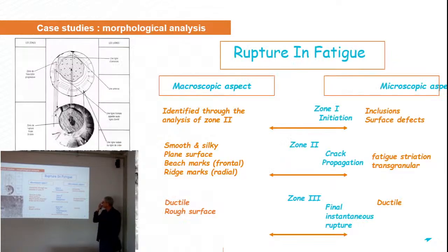Cases of fatigue are very interesting to analyze, because usually the fracture surface is very typical. You can see three zones, or very simply you can see two zones. Here, the first zone, where you can see that the surface is smooth and silky, and the second zone here, where the surface is very rough, okay? So when you have considered these two zones, generally speaking, by analyzing the zone of crack propagation, this one, you can find the third zone, which is here, the first one, where you get the initiation of the crack.